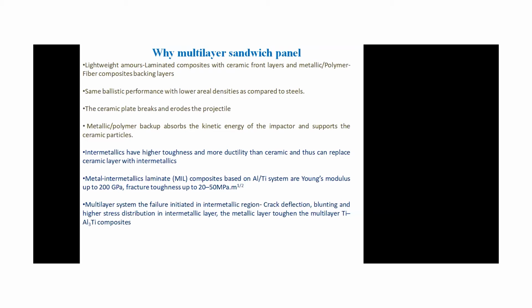The purpose of using a multiple-phase approach is that if any bullet hits your material, whichever phase is brittle first absorbs the energy. So any ceramic or intermetallic part which we added, which is normally slightly brittle, breaks and erodes the projectile, basically the bullet. And whatever metal part or softer part is there absorbs the kinetic energy of the impactor, because the harder part is basically hard. So it creates some kind of rubbing action with the projectile, because all bullets are basically metallic, mainly copper or steel, and they have a lesser hardness than your ceramic. So it basically blunts your projectile. So that way the projectile erodes.